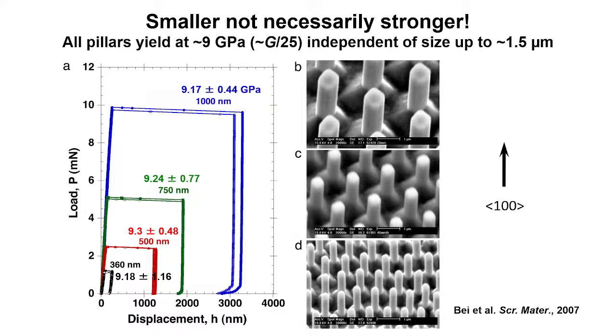So if you look at the loads, it looks like the smaller is getting stronger, but it's not the load that is important, it's the stress that is important. So when you divide by the cross-sectional area, these stresses are almost identical, right? So there is no smaller is stronger effect. They all yield at close to the theoretical strength, 10 GPa, give or take. And so these are the pillars from small to large. And so that sort of solved one of the puzzles of the UIUC and Dimiduk data. Smaller really is not stronger. What they were seeing was the effect of defects in their pillars.